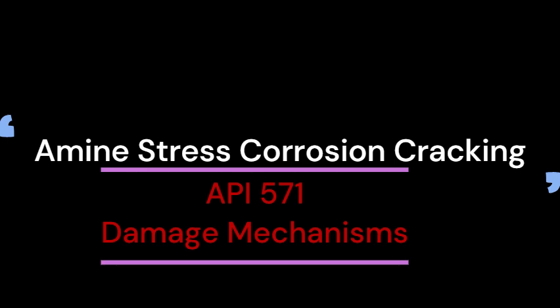Okay, say we find some crack that looks suspicious. How do we confirm it's actually amine SCC and not some other type of crack? Yeah, you need confirmation. That requires taking a sample and looking at it under a microscope, metallographic analysis. What you're looking for with amine SCC is that the crack path usually follows the grain boundaries of the steel. We call that intergranular. And often the cracks themselves are filled with dark oxides. Sometimes they branch out a bit too. That whole picture confirms the mechanism.